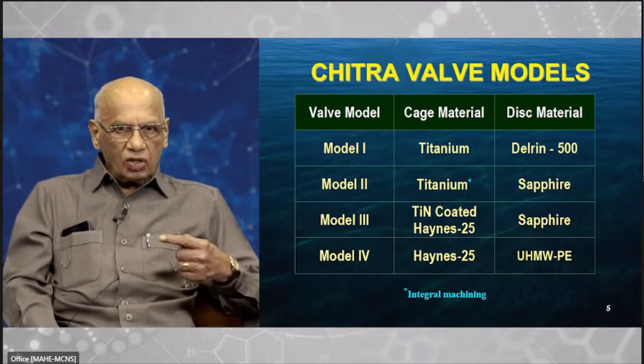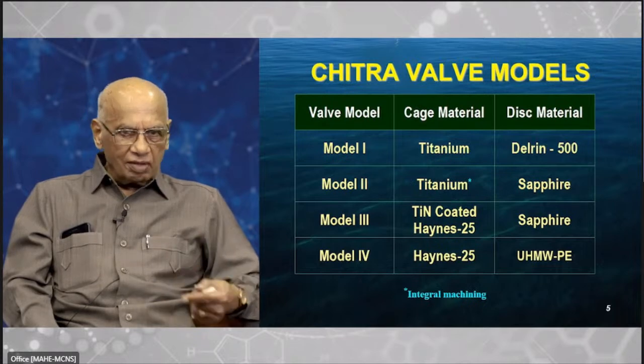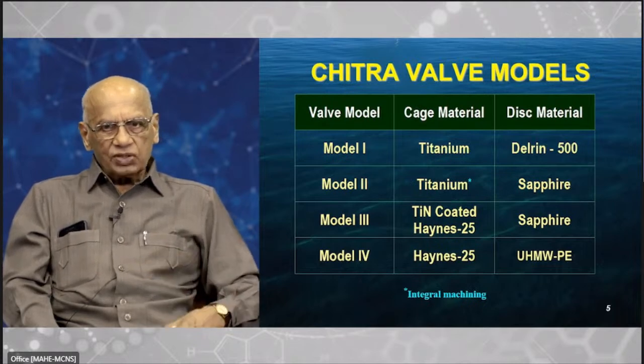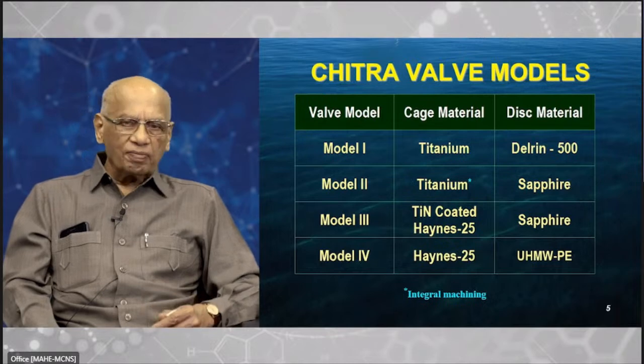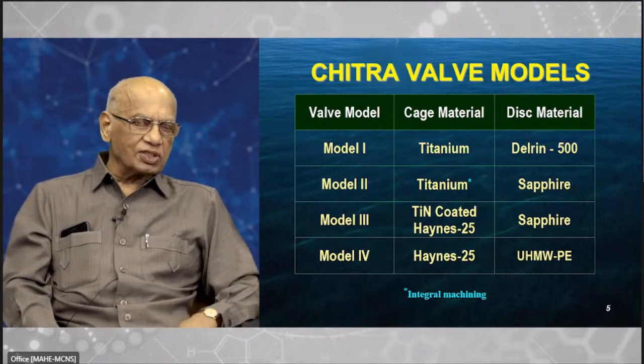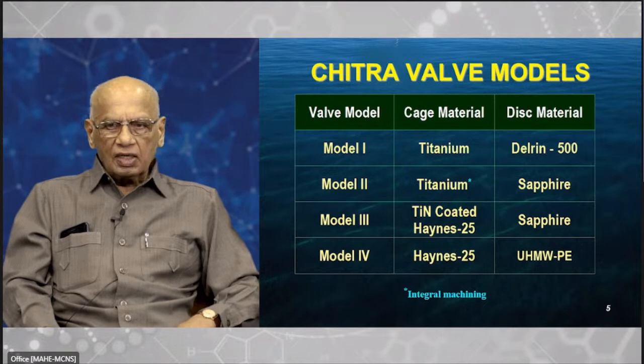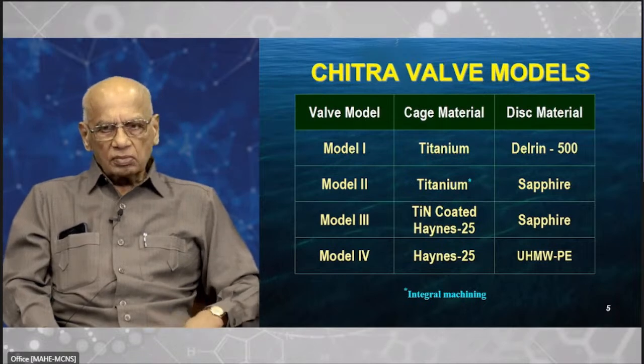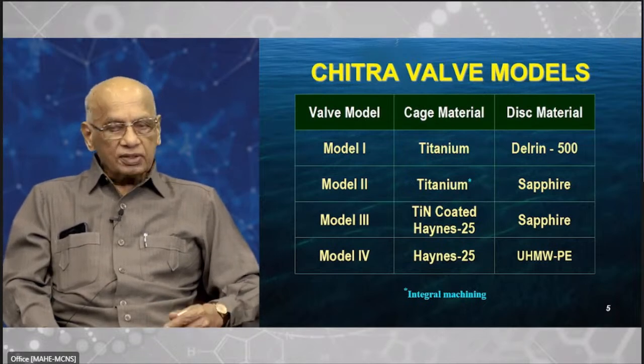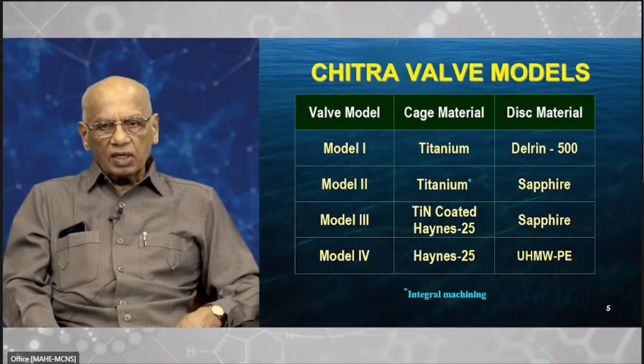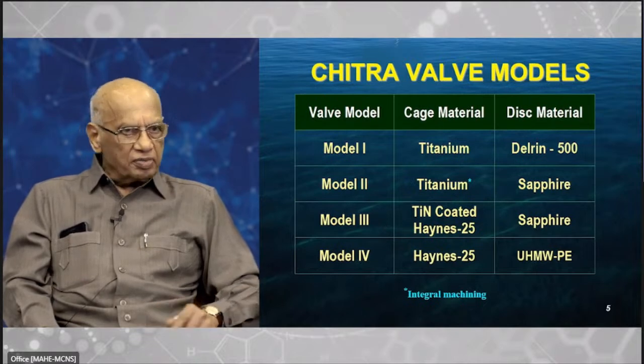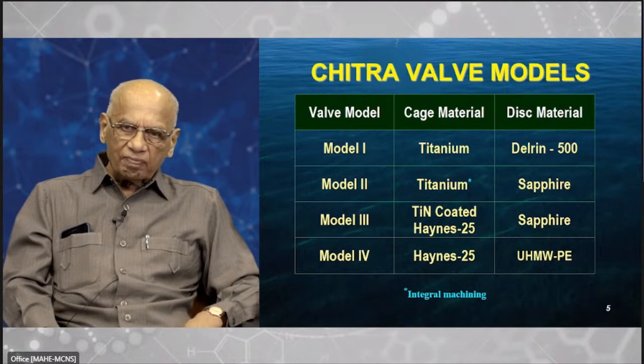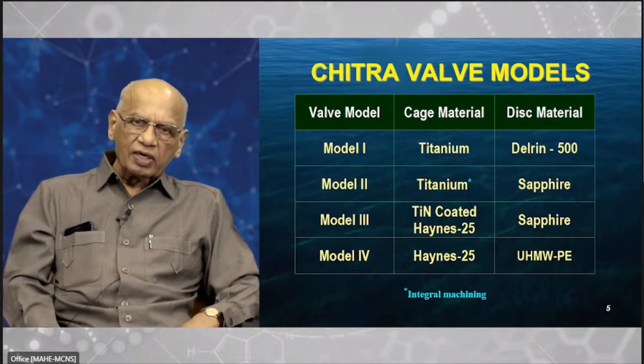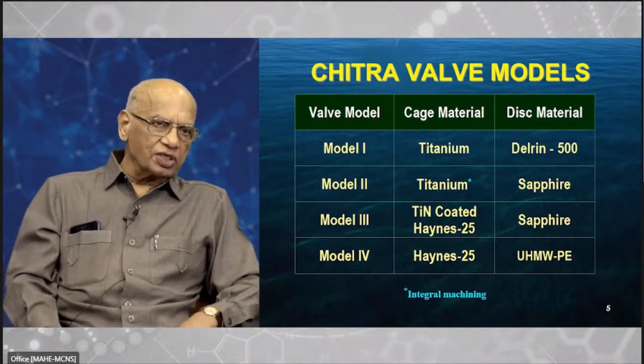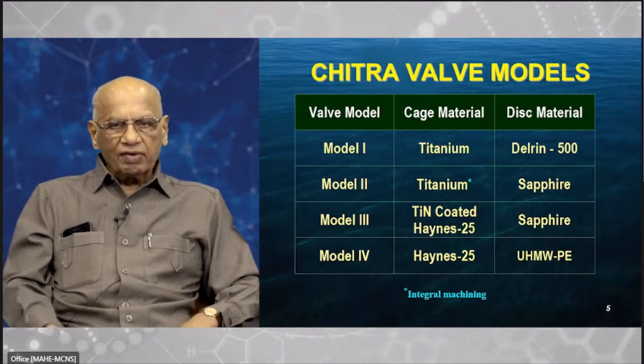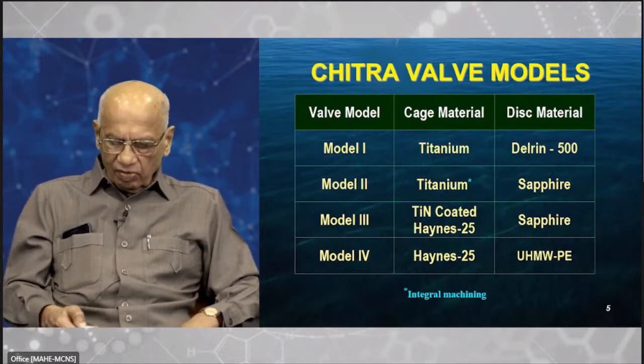Model 3, all these models changing because of failures, I'll come to that in a minute. Model 3 was titanium nitride coated HAYNES 25, that is a chromium cobalt alloy. And sapphire continued. And that failed. So we had model 4, where HAYNES 25 remained. We eliminated the titanium nitride coating, and ultra-high molecular weight polyethylene was the disc material. Now, why did we have to make these changes? That we will show now.